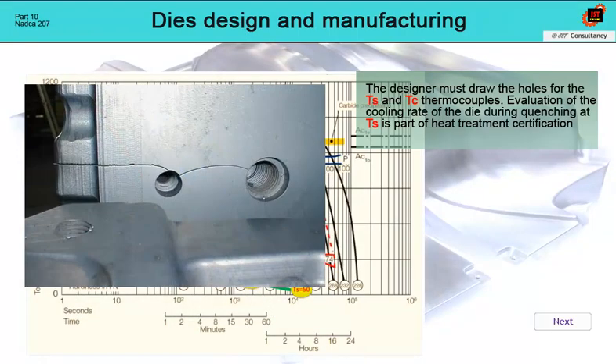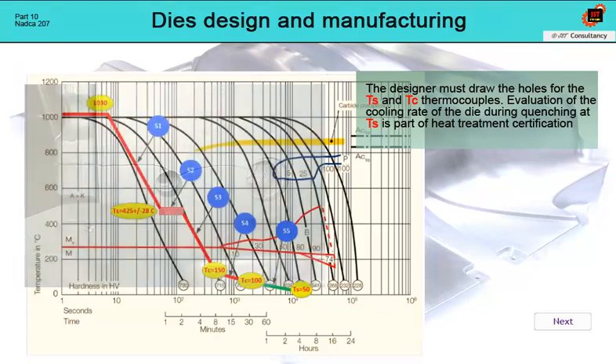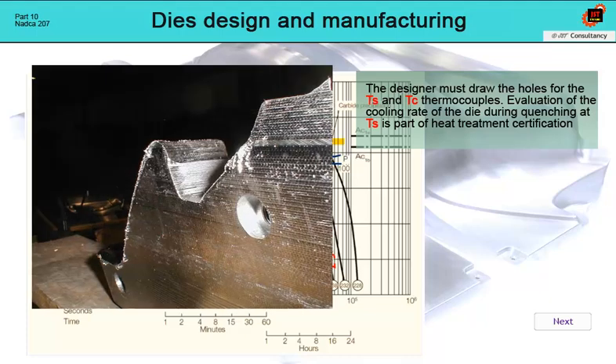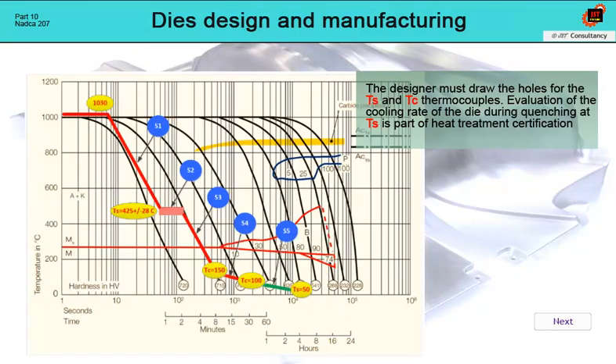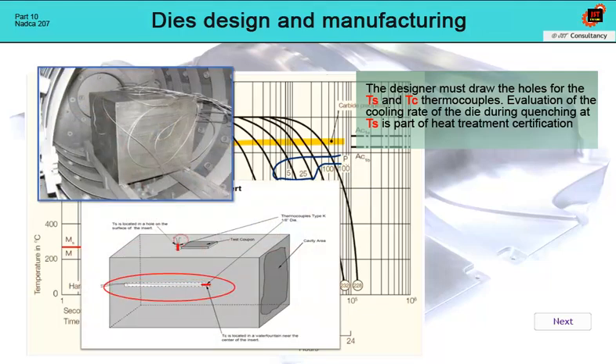Special attention should be paid to the threads on the periphery of the insert. The shapes must be cleaned of burrs, the outer edges should be chamfered. All risky transitions between the holes and the cavity should be treated. All points of potential concentration of tensile stresses must be removed. Massive inserts must have holes prepared for placing thermocouples, especially T-surface. Where EDM machining will be performed, the designer should prescribe the locations where the remelt layer must be removed.